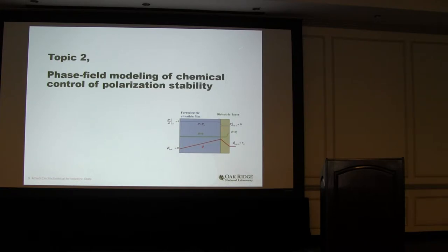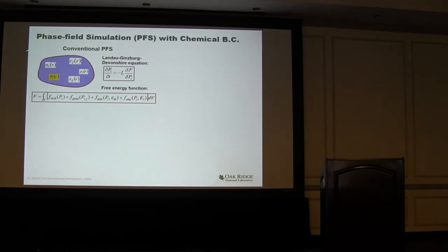Next, we move on to the phase field model, incorporating realistic chemical boundary conditions to study the chemical control of the polarization stability. The phase field model has shown its capability to model ferroelectric behaviors in the past 15 years. Basically, it is based on the Landau-Ginzburg equations to solve for the polarization as the order parameter to describe the structure.